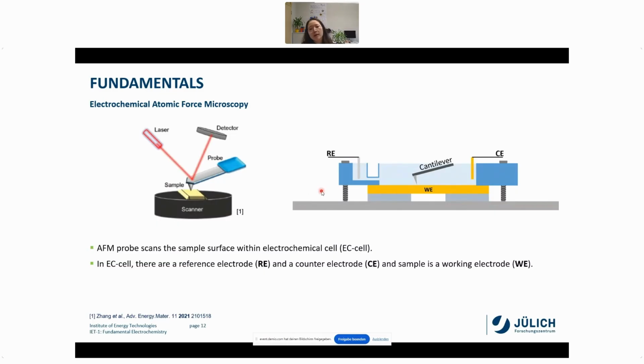So then how do we measure electrochemical AFM? For that, we need electrolyte in contact with the sample, and the sample is working as a working electrode. And the difference between air measurement and electrolyte measurement is that the cantilever is in the electrolyte, so the laser will travel from air to electrolyte, and the reflected laser will go from electrolyte to the air.